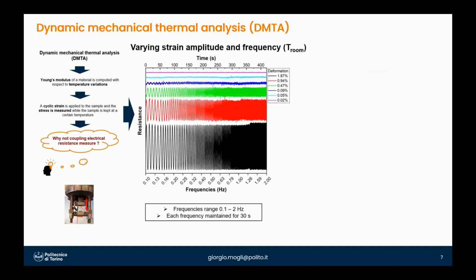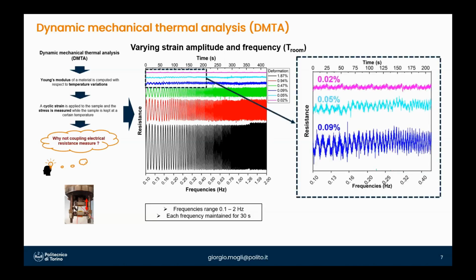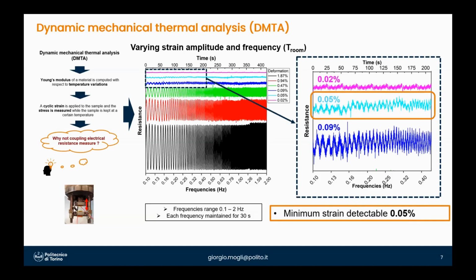Then, since the instrument allows us to apply small strains at various frequencies, several very small strains were evaluated at various frequencies, and here the resistance paths are reported. And as we can see from this zoom, the minimum strain detectable by this organohydrogel sensor was 0.05%, in which we can see in the blue light curve the cyclic deformations, which are reflected by the cyclic resistance